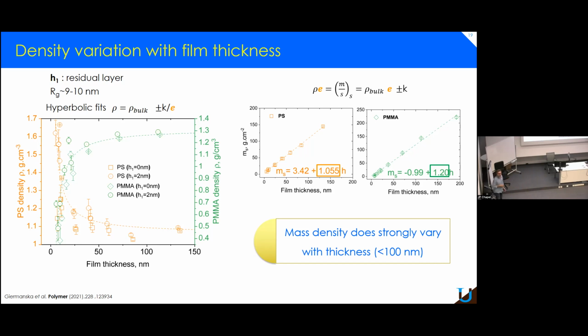You deposit the film directly on the quartz? Yeah. That's why it was a bit tricky, but yes, we coat the film directly on the quartz sensor, and after we put it in the QCM, and we dissolve it to be able to measure the amount of film. Let's say it's an average. Obviously, everything here is an average. Maybe closer to the substrate it is different, but it's an average.